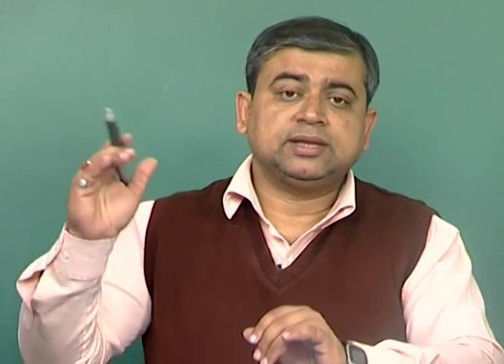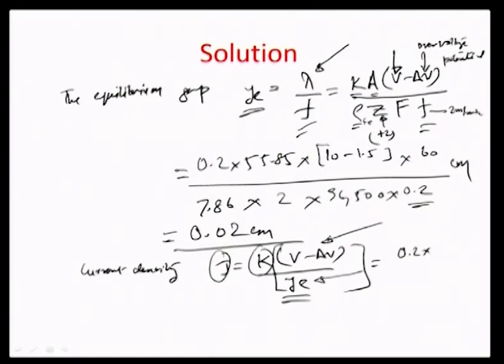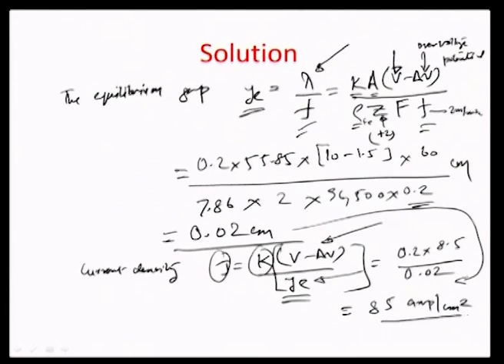So, effectively the available voltage between the two electrodes which can do machining is V minus delta V. And so, the current density, which is the ionic transport between the two electrodes, is actually equal to the conductivity times this available voltage per unit equilibrium gap Ye which is there between the tool and the electrode. So, this becomes equal to 0.2 times 8.5 by the new equilibrium gap which has been calculated from the previous step as 0.02 centimeter. And this you can represent as 85 ampere per centimeter square. Okay.